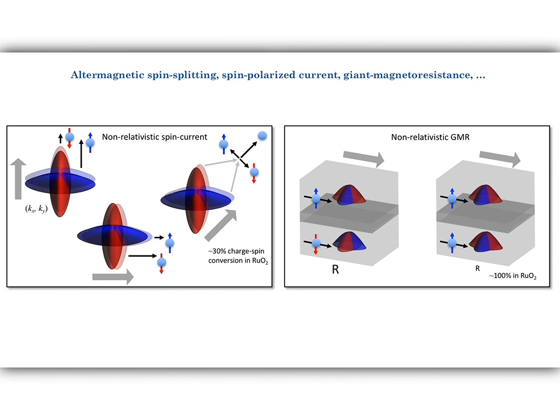And so this is reminiscent of ferromagnets. However, now when you apply the electrical bias in the orthogonal direction, you will also get spin polarized current, but now the spin polarization will be reversed. So you can reverse the spin polarization of the current by reorienting the applied bias. This is certainly something which is not observed in ferromagnets. And another unique feature is that when you apply this bias along this diagonal direction, your longitudinal current will be unpolarized. So this will be reminiscent of antiferromagnets.